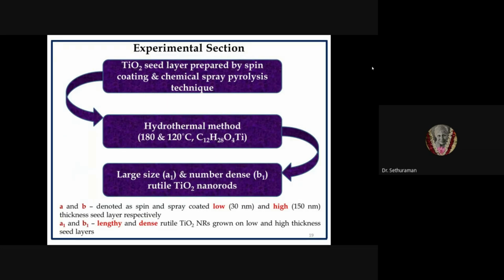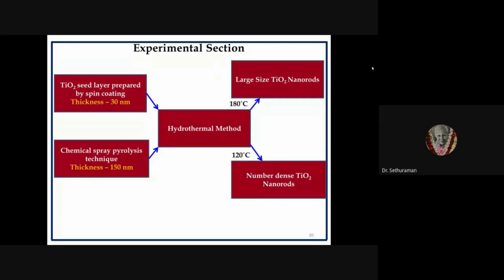So how did we carry out this experiment? We prepared the TiO2 seed layer by spin coating technique. We optimized the thickness at about 30 nanometer, and by using the chemical spray pyrolysis technique, the TiO2 seed layer is prepared with a thickness of 150 nanometer. One we have taken as a lower thickness, 30 nanometer, and the other as a higher thickness, 150 nanometer. So a very simple hydrothermal method using two different temperatures.